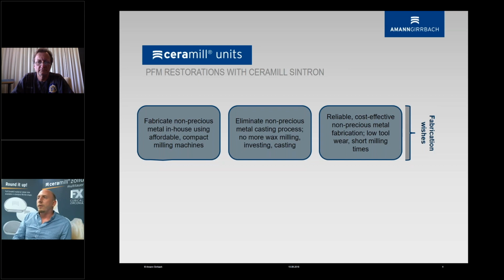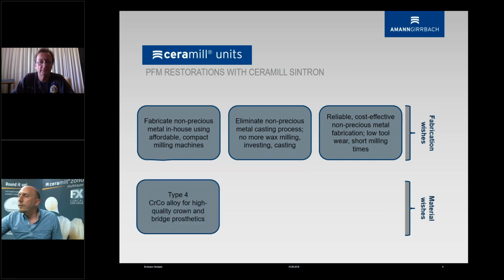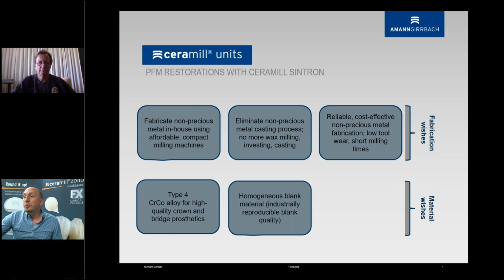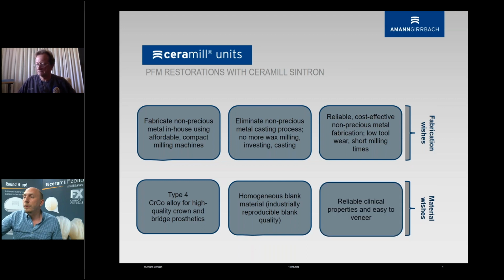And same wise, the tool abrasion is relatively low, and therefore you get a low cost. And then it shrinks. That maybe gives you another idea. It shrinks about 11%. So from the material wishes, not only fabrication wishes, but the material wishes: high-quality, homogeneous blank material, and a reliable process with easy properties for veneering, porcelain, etc.